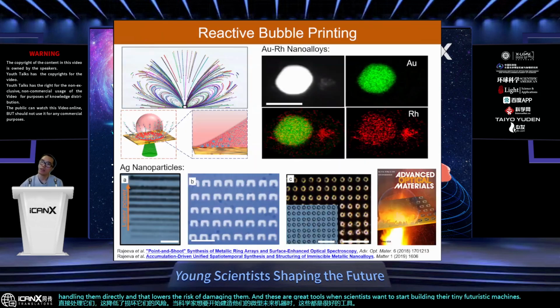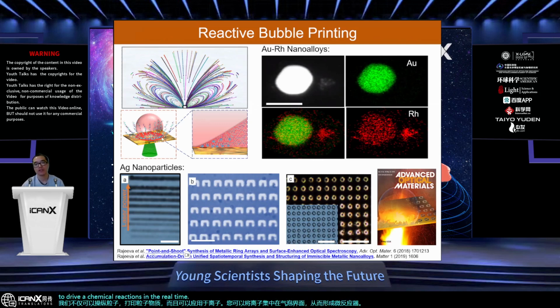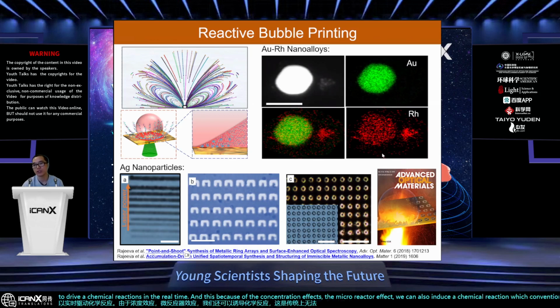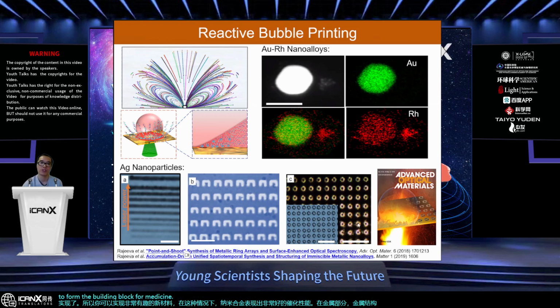So we can not only manipulate particles and print the particles on a substrate, but this can also apply to ions. You can concentrate the ions at the bubble interface, which forms a microreactor to drive chemical reactions in real time. And because of the high concentration effect, the microreactor effect, we can also induce a chemical reaction which conventionally cannot be achieved. So you can achieve very interesting new materials which show very good analytical properties, in this case, the nanoalloys, or the metal structures to form the building block for metal surface or metal material.